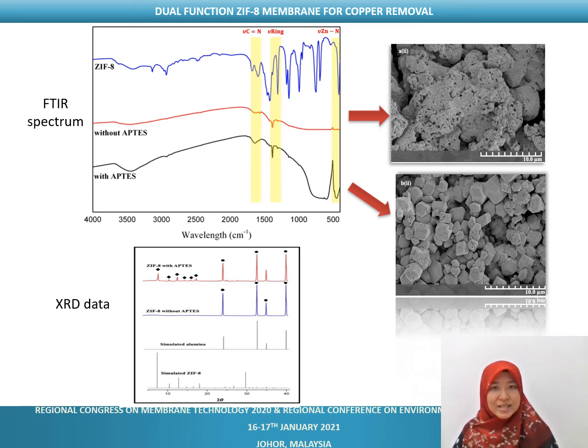When we look at the XRD peaks for ZIF-8 grown on APTES-modified alumina, there are good agreement with the previous reports, thus confirming the formation of a pure crystalline ZIF-8 phase. While for the unmodified alumina surface, the growth of ZIF-8 on top of the membrane seemed to be unsuccessful, as the presence of ZIF-8 can only be detected as traces.